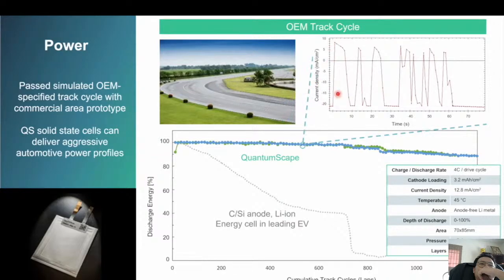So this shows current density over time of one lap around the track, with accelerations of 4 or 5 C here, and regenerative braking of 1 or 2 C, repeating these very aggressive accelerations on the straightaway and braking going into the turns, and repeat around one lap of the track. And then we repeat to get to about 9 or 10 laps around the track until the battery is fully depleted. And then we go into a 4C fast charge. And then we just repeat that cycle of laps around the track until the battery is fully depleted and 4C fast charge. Do that continuously.